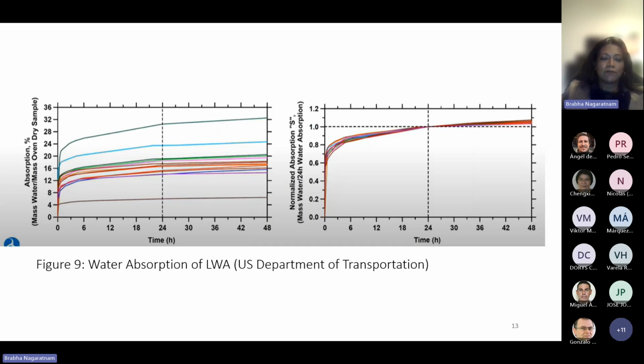So here I have the water absorption properties of different types of aggregates that were found. You can see that at 24 hours, which is the general standard for water absorption tests, the range is really high. It can be, like I said, 30% water absorption capacity. However, when we normalize the values at 24 hours, we find that all the aggregates reach 1 at that point. This is because the water absorption peaks at 24 hours, and after that it stabilizes, up to 48 hours. So it's within that first 24 hours that the water absorption is really high.